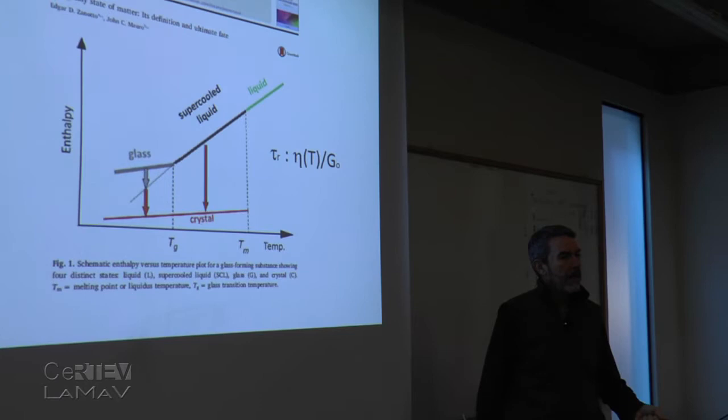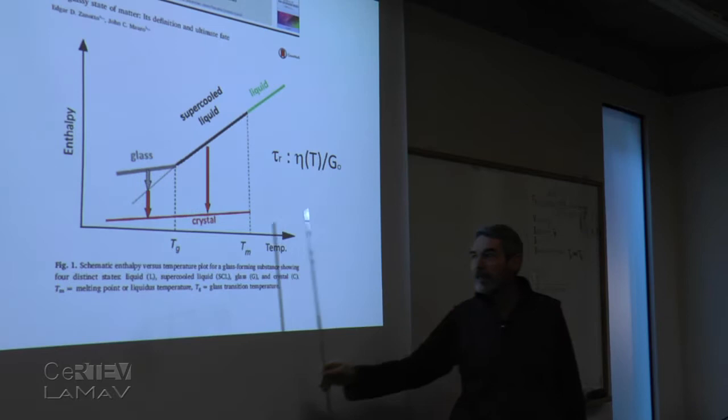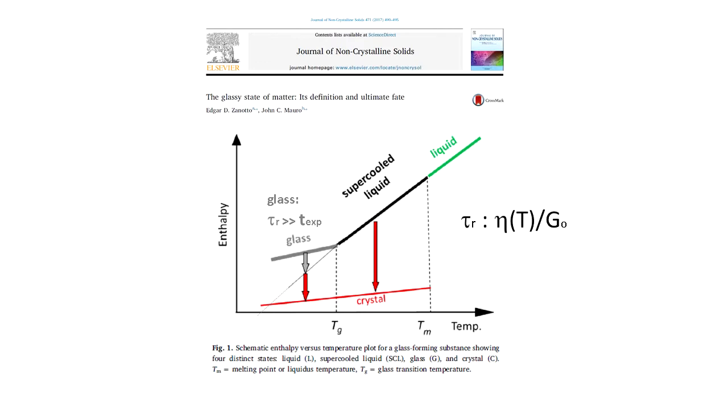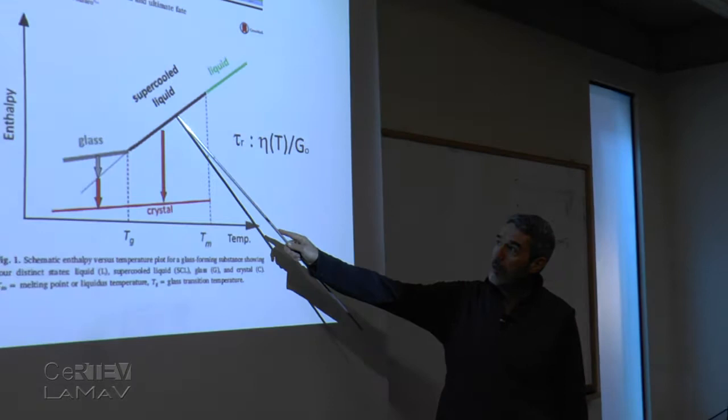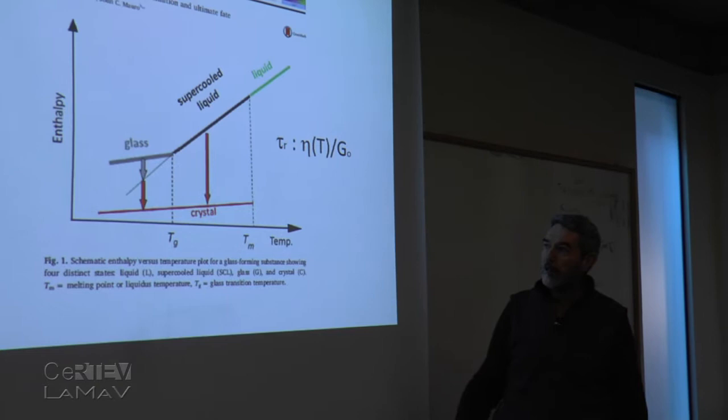And the time it takes to crystallize depends on the temperature and the chemical composition of the material. For instance, metallic materials crystallize extremely fast. Or liquids like water, or ionic liquids in general, crystallize very fast. These mixed ionic covalent materials, such as some oxides, silicates and borates and germanates and tellurides, crystallize slowly enough so we can supercool the liquid, supercool it until we reach a certain range of temperatures